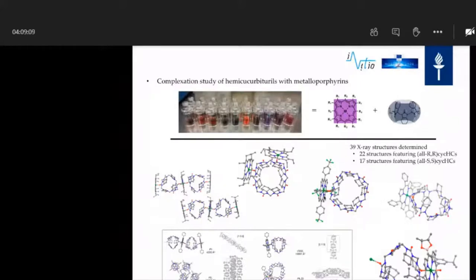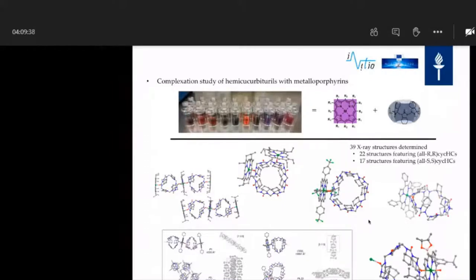We obtained, as you can see — I haven't shown all the structures but here are some examples — in total 39 X-ray structures. We mixed one equivalent of the metalloporphyrin with one equivalent of the HC in methanol and DCM. Although we always used a 1-to-1 ratio, not all products were 1-to-1. On the right side we can see 1-to-1 complexes, but sometimes we also observed 2-to-1 or even 2-to-3 discrete complexes.